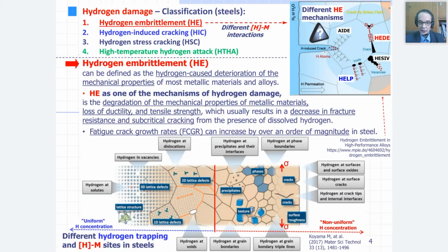in different traps, hydrogen traps in our material. Typical traps are precipitates and their interfaces. Also, hydrogen could be located at phase boundaries, at grain boundaries, at grain triple lines. And as you can see on the right part, hydrogen also could be concentrated at surface cracks. It represents a strong stress concentrator, where we have a strong accumulation of high hydrogen content at the crack tip. And other internal interfaces like pre-existing cracks or voids.